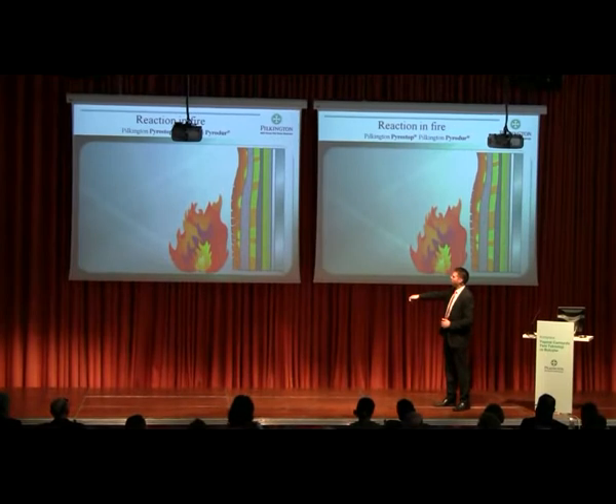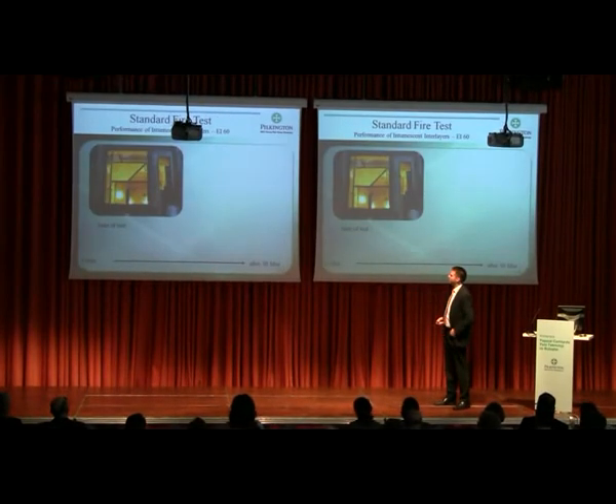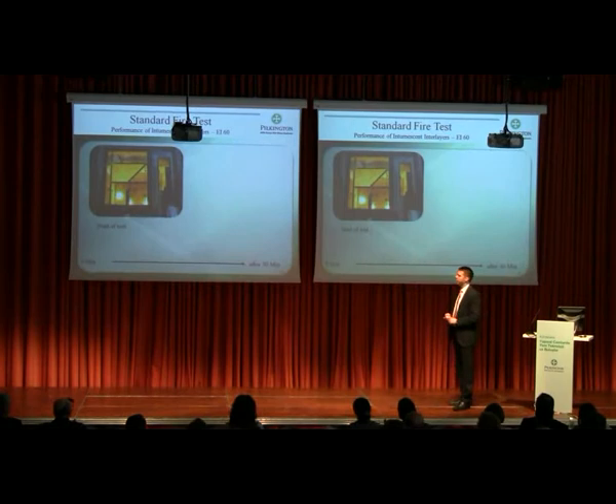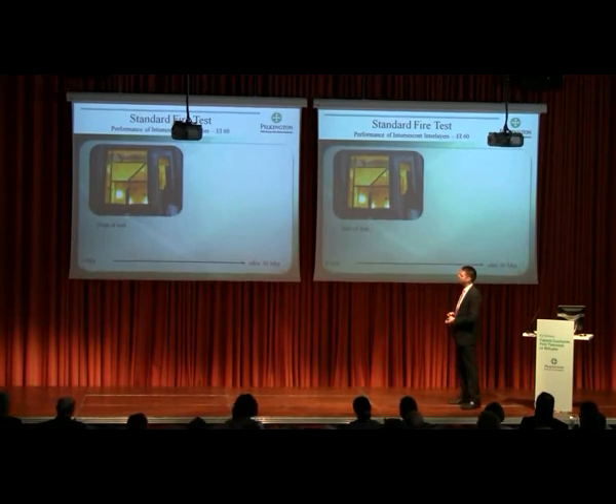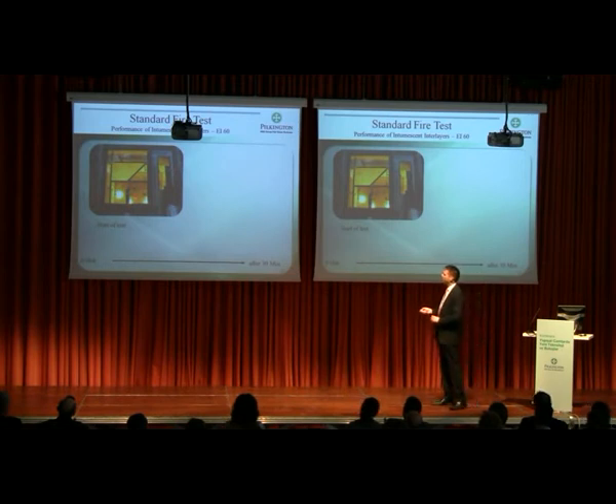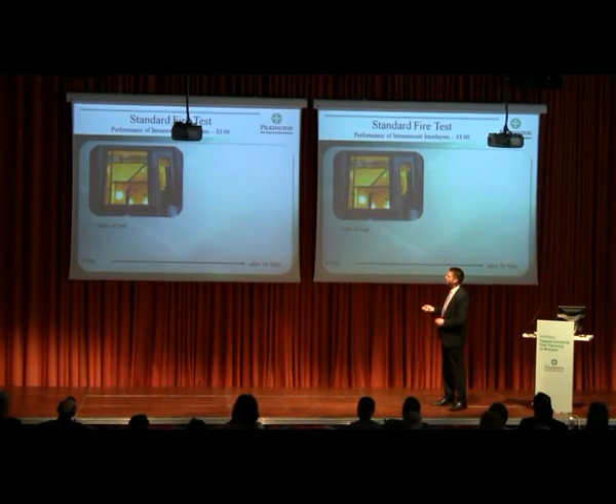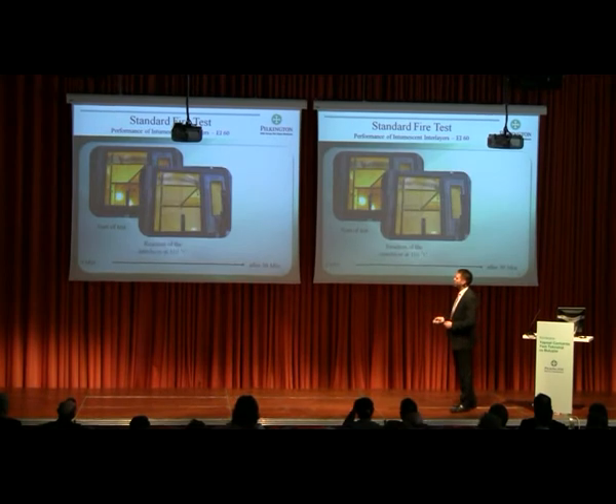All interlayers performed. In a standard fire test, it might look like this. We have a steel frame installed in a 4 meter by 4 meter furnace. The burners are starting, and you can still see the back of the furnace after 1 minute. But you can already see that here is the hottest point in the furnace, and the first interlayer has already started to react.